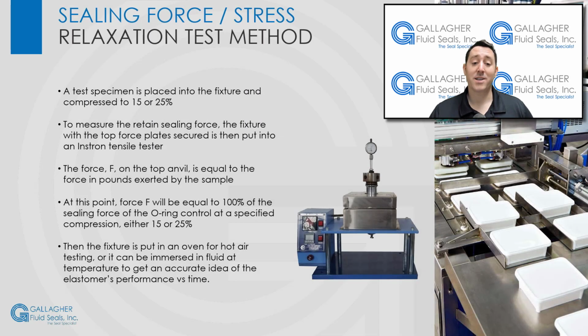When the stress relaxation test fixture is used, a test specimen is placed into the fixture and compressed to 15% or 25%. To measure the retained sealing force, the fixture with the top force plates secured is then put into an Instron tensile tester. The force, F, on the top anvil is equal to the force in pounds exerted by the sample. At this point, force F will be equal to 100% of the sealing force of the O-ring control at a specified compression, either 15% or 25%.